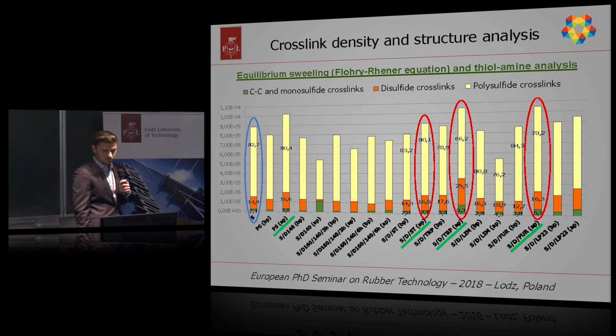But when we look at the results of thiol-amine analysis, we can see that the participation of various crosslinks evolves proportionately to increasing or decreasing crosslink density. However, what is a little bit interesting is that samples cured with copolymers after purification contain less polysulfide crosslinks and simultaneously more disulfide, monosulfide, and carbon-carbon crosslinks than the reference sample, and it can be a little bit surprising at first glance.